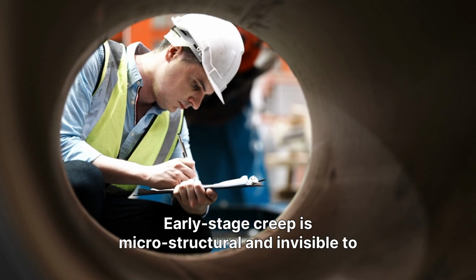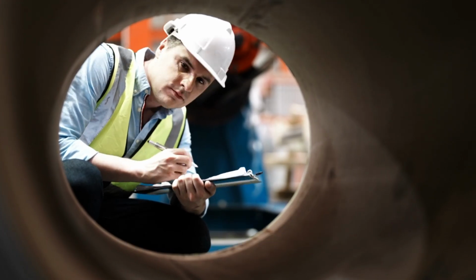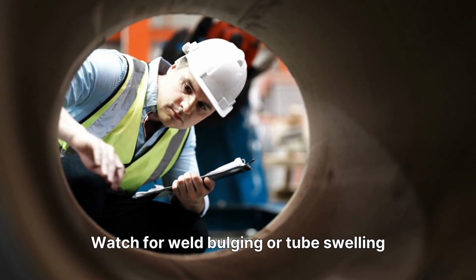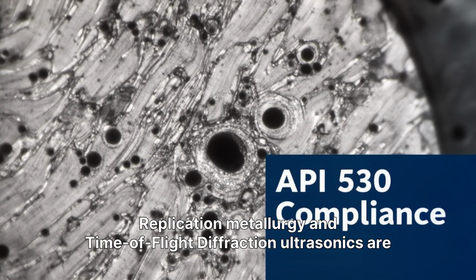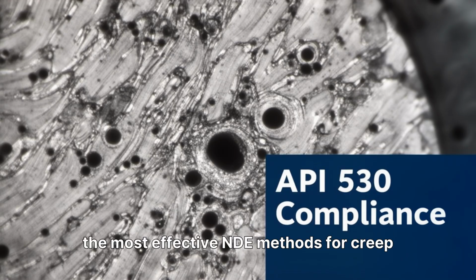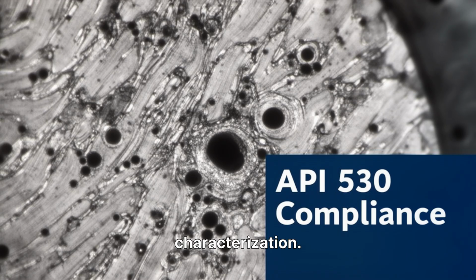Second, creep damage. This develops in equipment operating above 370 degrees Celsius for carbon steel or higher for alloys. Early-stage creep is microstructural and invisible to the naked eye. Watch for weld bulging or tube swelling as permanent deformation. Replication metallurgy and time-of-flight diffraction ultrasonics are the most effective NDE methods for creep characterization.